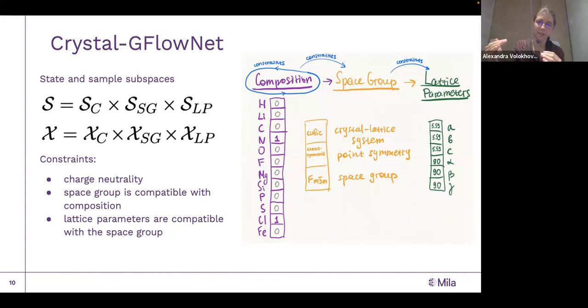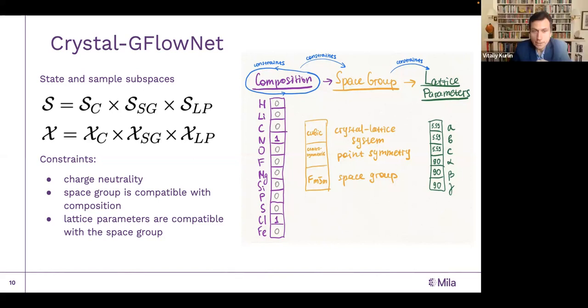And some space groups have quite high minimal multiplicity. I don't remember the name, but there was some space group which has a multiplicity of 16. It is the minimal multiplicity for all the possible positions of the atoms. And it means that if we put one atom of, say, lithium, we will need to repeat it 16 times within the cell. So if we have some composition with less than 16 atoms of this type, we just will not be able to satisfy the symmetry constraints for the space group. Yes, thank you very much.